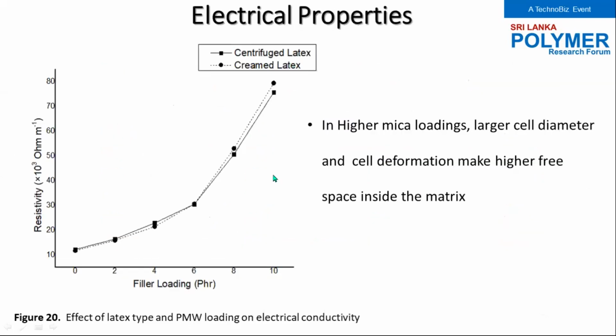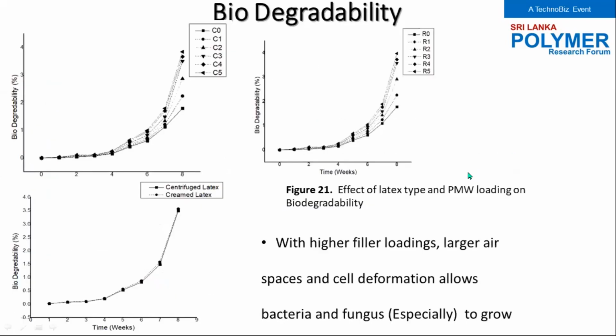And the electrical resistivity I have measured, a huge escalation of the resistivity could be observed, because at higher mica loadings we have identified larger cell diameters and cell deformation. So because of that, the higher free volume of air makes higher electrical resistivity.